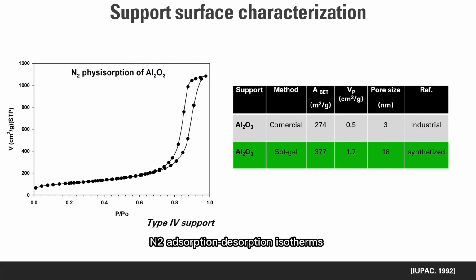This figure shows nitrogen adsorption desorption isotherms of the alumina support, which correspond to a type 4 isotherm and type H2 hysteresis, which are characteristic of mesoporous cylindrical pores with uniform size and shape, showing that the sol-gel supports synthesized have better properties than the industrial support.